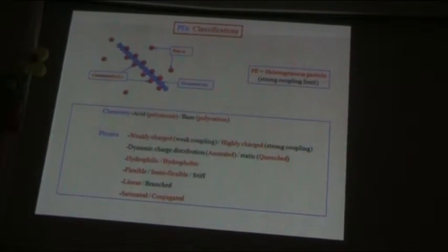If the chemical charge of the polymer is high enough, there is a threshold, and of course there is an instability. To avoid this instability, some counterions are condensed onto the macroion.